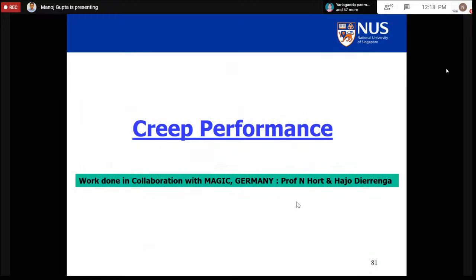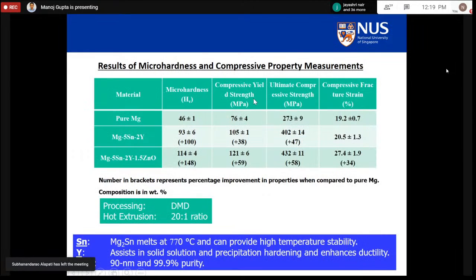monolithic material. We also did work for high temperature characterization, which is called the creep failure of material at high temperature, with the researchers Norbert Hort and Hajo Dieringa in Germany in Magnesium Innovation Center. And we gave them a new material containing tin and yttrium. Of course, we found an increase in the hardness, increase in the strength values, as you have seen. And when you convert that into a nanocomposite, the hardness goes up further and the strength goes up further.